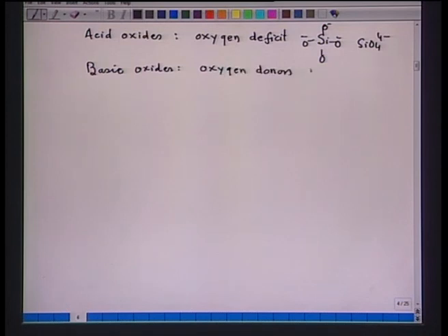For example, if I take calcium oxide, it will give me Ca2+ and O2-. So, Ca2+ does not form a complex like SiO4 4-. So, basic oxides are oxygen donors, and these O2- ions can move freely into the melt. Now, what can we do if we want to reduce the viscosity of acidic oxides? That is only possible